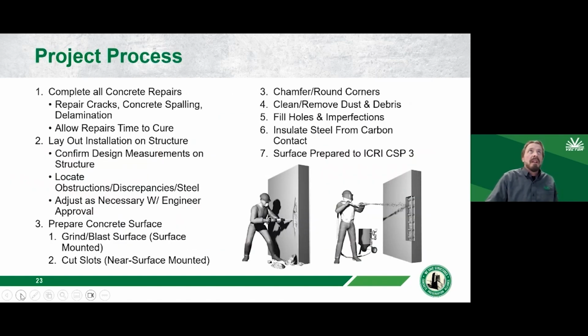The project process is fairly straightforward, right? We repair the cracks, usually by epoxy crack injection, and concrete spalling, restore the concrete to its original cross section, and then allow for those repairs to cure. Typically, when we know we've got to do repairs and then do FRP right after, we'll use a high performance repair mortar. Again, it's going to cost a bit more, but we're going to save on time. So we want something that sets fast, sets hard, hydrates quicker, so we can get on it and install the FRP quicker.